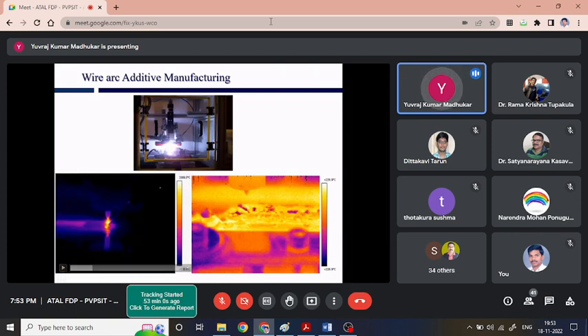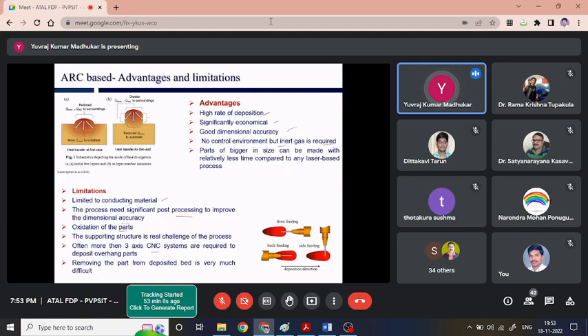In case of TIG-based additive manufacturing, since we have to feed the wires separately, it depends on the direction of feeding. Like in this case, we are moving in this direction and the wire feeding is going to be from the front. So depending on the direction of wire feeding, whether we are going for front feeding, back feeding or side feeding, it has been observed that the bead properties, the bead width W and bead height, change, as well as the amount of input parameters required. So in the case of these additional wire feeding based WAAM methods, like WAAM TIG and WAAM plasma, we have to take this into consideration as well. The wire feeding direction does play a certain role. Now this limit, I'll explain it later.